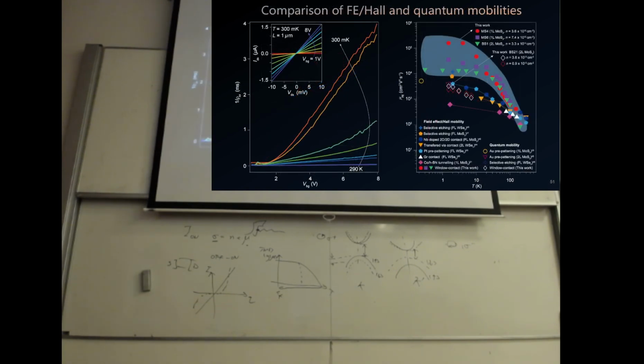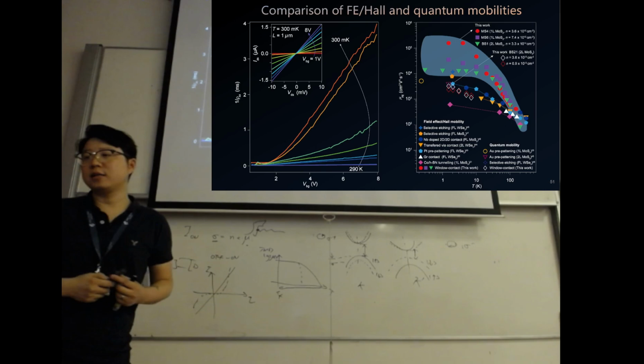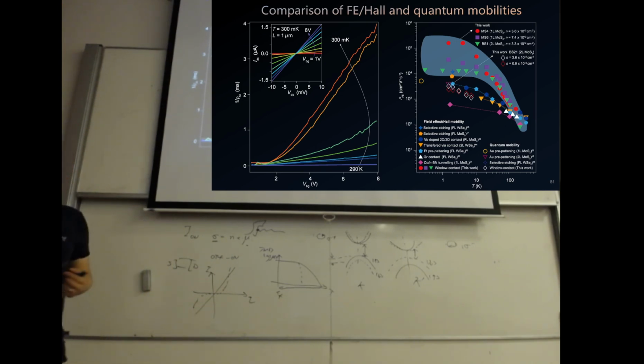Okay, so then we can have a look again. Sorry, the color is a little bit hard to see in the back, I guess. But anyway, we can have a summarization of all existing two-dimensional semiconductors, from, for example, MoS2 and tungsten diselenide, and so on. So using this bismuth contact and the thermal evaporation together with glovebox sealing, we have obtained the highest mobility ever in all semiconductors at low temperature limit. So this is about 10 to the 5th.